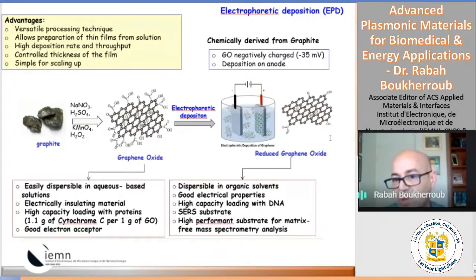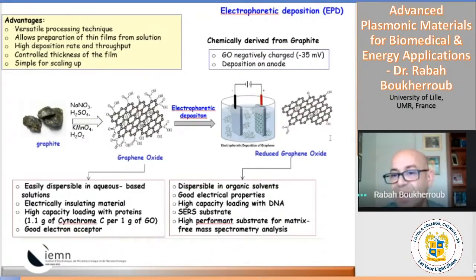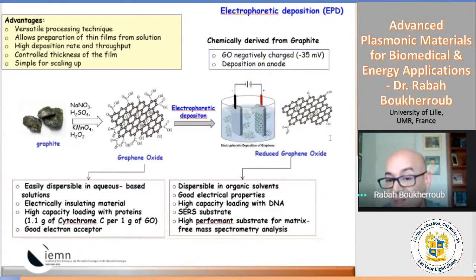Now, whatever I covered was mostly on CVD graphene, but as I told you, with chemists, we really prefer working with something which is cheap and easy and available. It's this chemically derived graphene. What people mostly do is take a single drop or a few drops of this onto any substrate, but you end up with a relatively thick layer. So most of the time you really lose the graphene characteristics and properties.